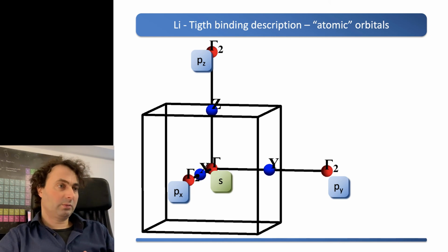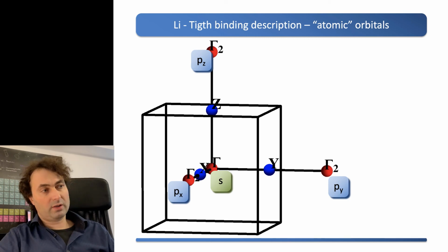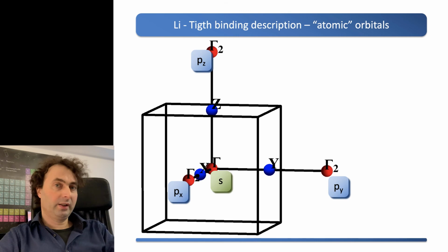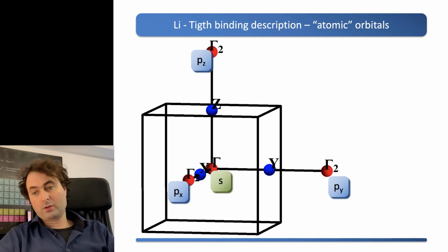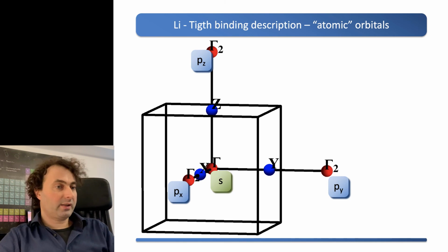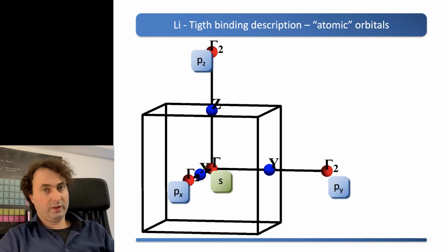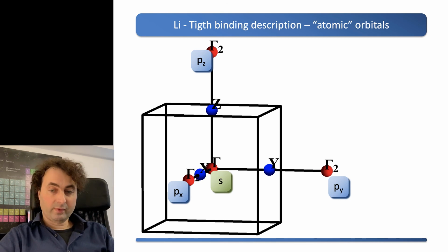When you have d orbitals, then there are always 2 orbitals at the same energy that are available. So this idea that you fill up the entire phase space and therefore you have no Coulomb scattering is no longer valid. So there is always some possibility to do Coulomb scattering, and when it breaks down, it starts to break down hard, because we make an approximation where we neglect the large part of the Hamiltonian instead of the small part of the Hamiltonian.